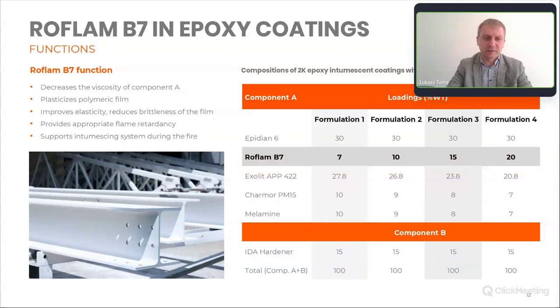Important thing, because without appropriate plasticizers, the epoxy coatings are very brittle and their performance might be limited. So the usage of Roflam B7 significantly improves the coating parameters, and it's worth emphasizing once again its function as a plasticizer. So Roflam B7 decreases the viscosity of epoxy resin, provides optimum mechanical properties, but also as a flame retardant supports the intumescent system. For better understanding of the influence of Roflam B7 on those parameters, I would like to show you the results of our application test we did in R&D.